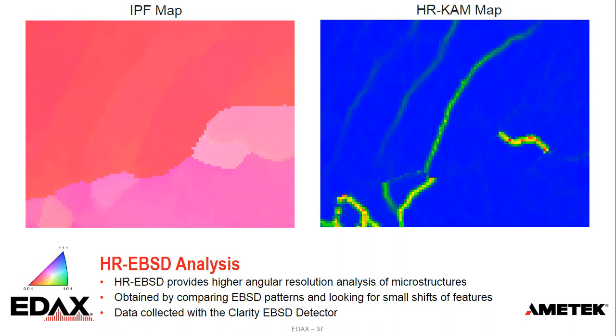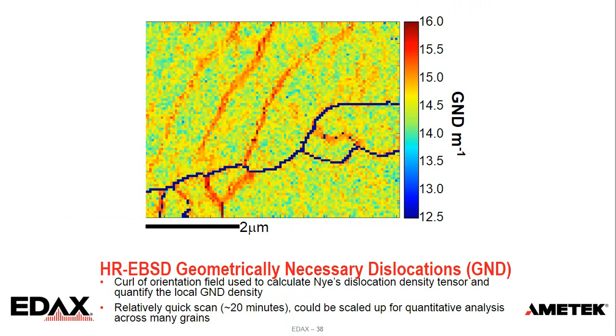This can then be used to measure the GND, or geometrically necessary dislocation density. Depending on what the misorientation is, there's a certain amount of dislocations that are necessary to create that angular change. It's the curl of the orientation field that's used to do that calculation. So we can figure out where the GNDs are present and visualize those.